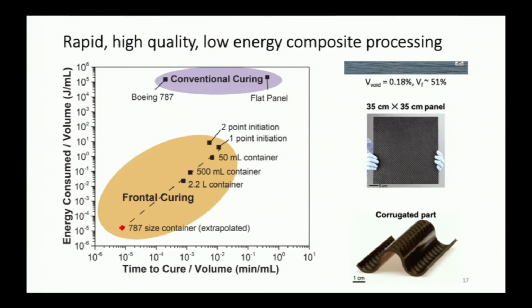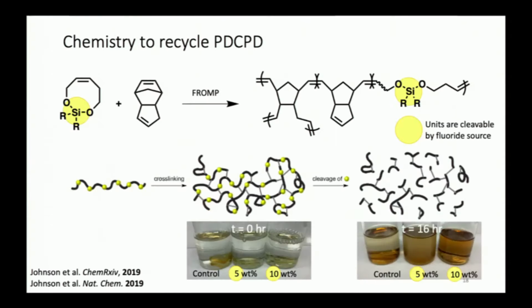And the quality of these composites is comparable to a typical epoxy carbon fiber based composite material. That material that I was describing is not easily returned back into a useful feedstock. It's a thermoset material, and so it's not even meltable. And so at this point, you then really need to go back to the chemist and say, what can we do in order to put in a means by which we could trigger the return back to useful intermediates